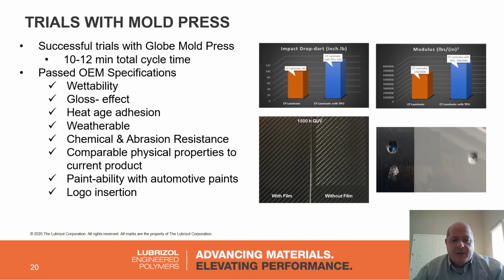Here are some additional results on the carbon fiber. We did all of the testing for Florida weathering, looking at the gloss, how it heat ages, chemical and abrasion resistance, checking physical properties of the carbon fiber, and checking that the film could be painted. As another item, it's also possible to print a logo on the film. So if you wanted some kind of artwork or something of that nature, it could also be part of the film sitting on top of the carbon fiber.